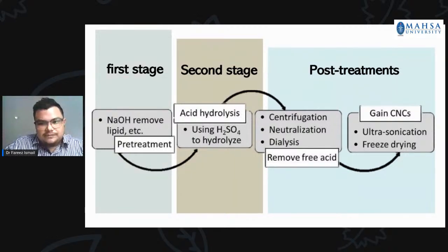During the first stage, the extractives, the monomers or dimers and polymers of fat, free sugar, tannins, hemicellulose, and lignin have to be partially or totally eliminated from the raw material based on the specific pretreatment methods. The second stage is usually dedicated to production of cellulose nanocrystal. It's the hydrolysis to ensure the elimination of the amorphous domains from the pristine cellulose, and it gives rise to the production of CNC with relatively high crystallinity. The acid used can be sulfuric acid, hydrochloric acid, or they are also using some organic acids.